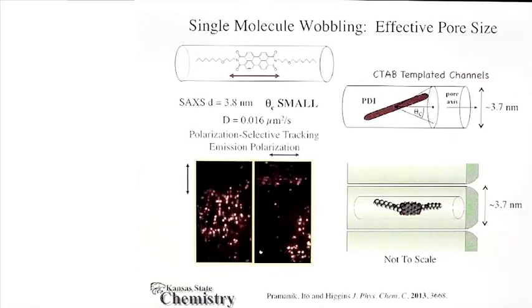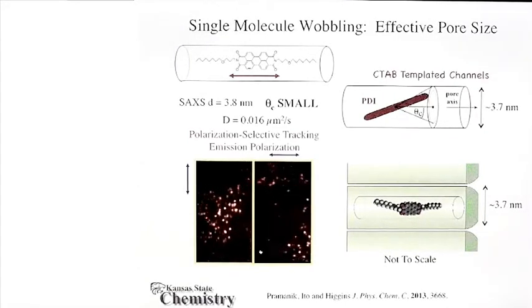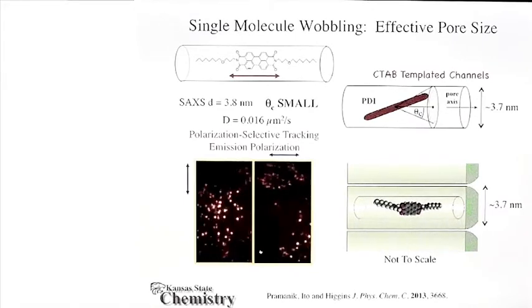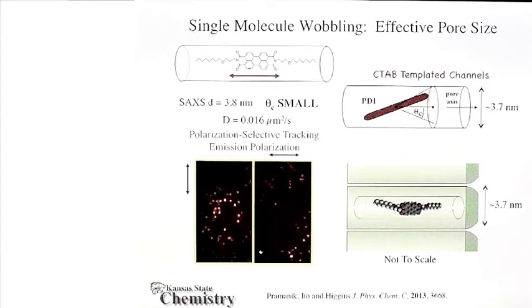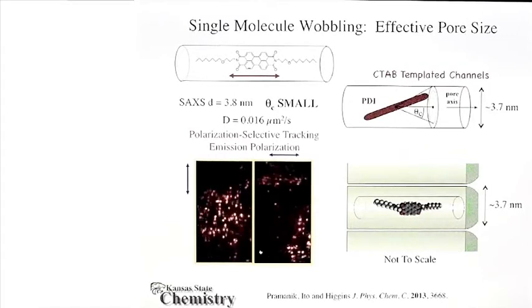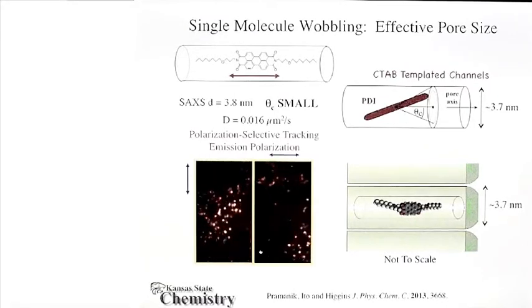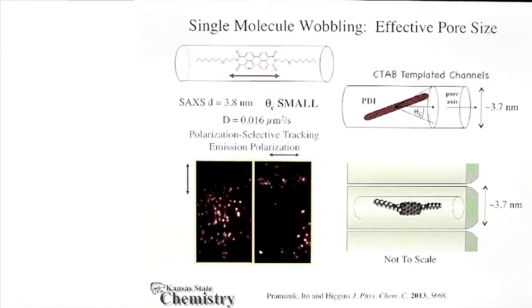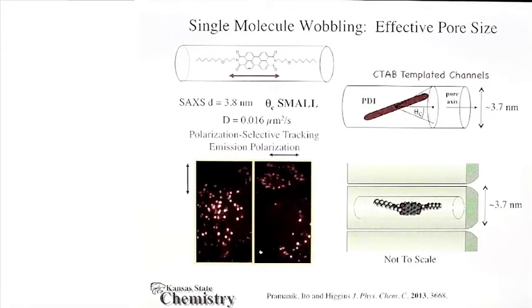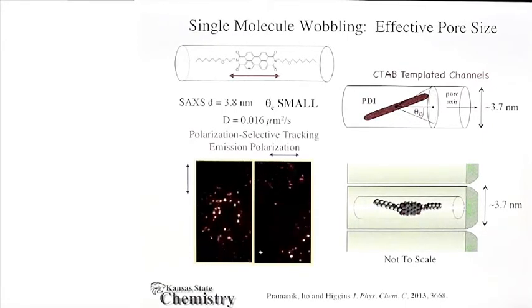However, quantitative analysis of the single molecule tracking data demonstrates that there is indeed some depolarization of the fluorescence, indicating that the molecules exhibit some orientational motions.